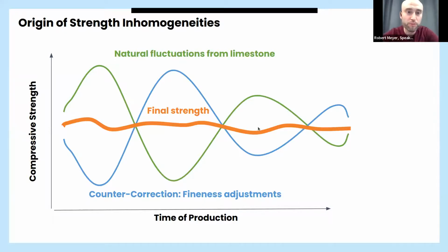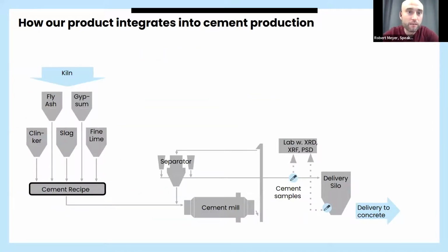So if I want to produce a cement with 50 megapascals, I can really make sure that year round I will produce a cement that will have 50 megapascals of compressive strength. So here's how that works in the final step of the cement plant, the actual grinding of the cement. What you can see here are the raw ingredients: clinker, that's the main ingredient, and then the supplementary cementitious materials like slag and fine limestone. All of them get chucked together and ground in the cement mill. Then there's a separator or filter step where you can separate fine from coarse particles, and stuff that's still too coarse has to take more tours through the cement mill.